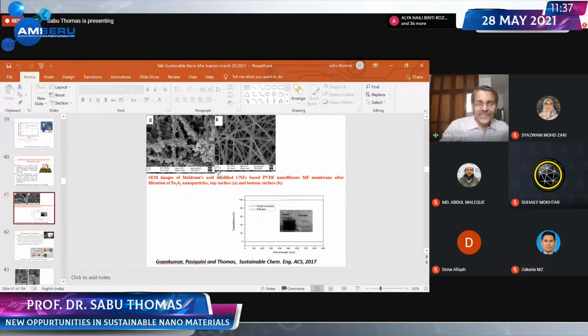And you might be surprised to see the separation efficiency. Look at this. All these suspended nanoparticles, these are all metal oxides, iron oxide, they're all retained on the top surface of the filter, because they are bigger in size. Look at the bottom part of the filter, electrospun PVDF. No particles. And look at the impure water, which is black, because of a lot of iron oxide particles. It's completely opaque, no transmission of light. After filtration, you get pure water, 100% transmission. That means we could remove almost all the suspended particles.